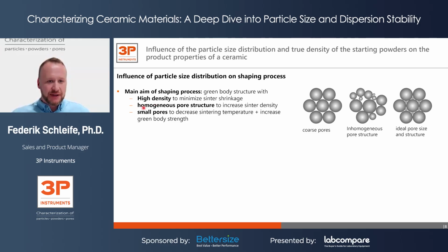So why is a homogeneous pore structure needed? Because different pore sizes will behave in a different way during the sintering process. The larger the pores are, the higher the sintering temperature that needs to be applied. The smaller the pores are, the lower the sintering temperature could be. So when you have an inhomogeneous pore structure, you might have some large pores next to some small pores. When it comes to sintering, those larger pores might even grow, which later gives a lower density of the final piece after the sintering process.